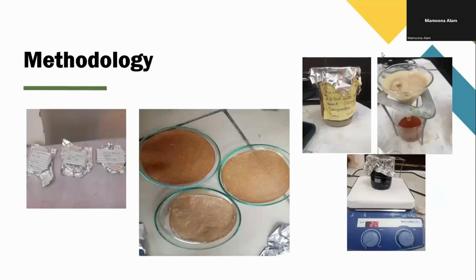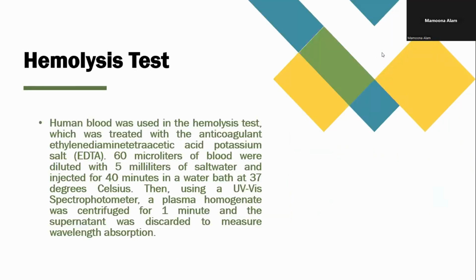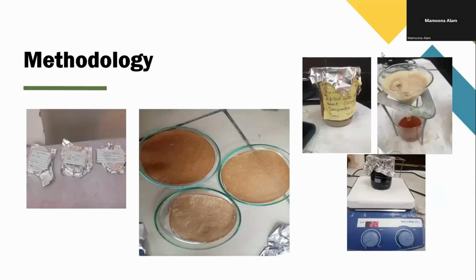This was the methodology. I used filtration of the crab shells. Okay, here you can see the petri dishes. I actually used industrial PVC. I mixed the industrial PVC with the chitosan I obtained from the crab shell, and you can see the membranes are quite homogeneous in the mixing. So I easily removed them from the petri dishes, and then I went for the testing.